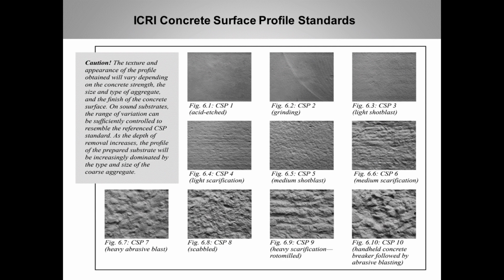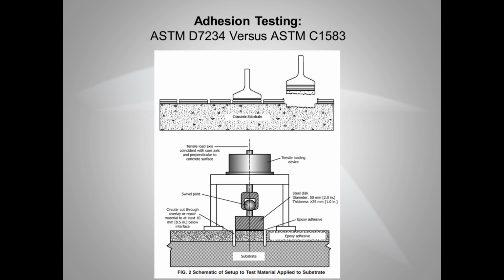The International Concrete Repair Institute has a method for identifying concrete surface profiles, and you can see there's acid etching, grinding, and so forth. Most of the surface profile that we would end up with would be a CSP 6 or greater, and that is one of the things, for example, that we teach our installers. We also teach our installers about adhesion testing. There are many different ways to perform adhesion testing. In fact, at the end of this program, you're going to see that we have a technical bulletin that we've issued on the subject.